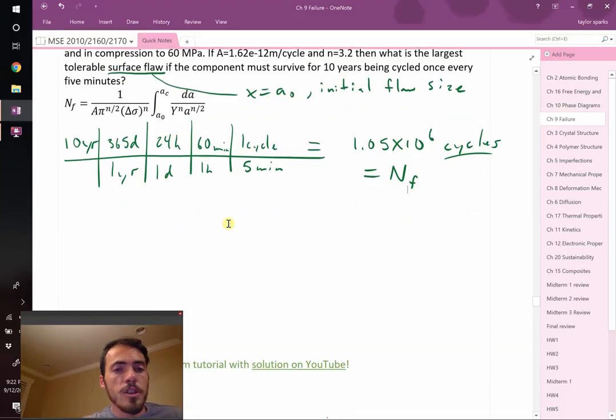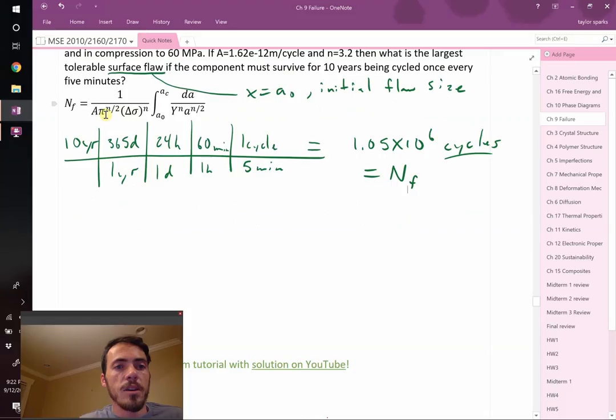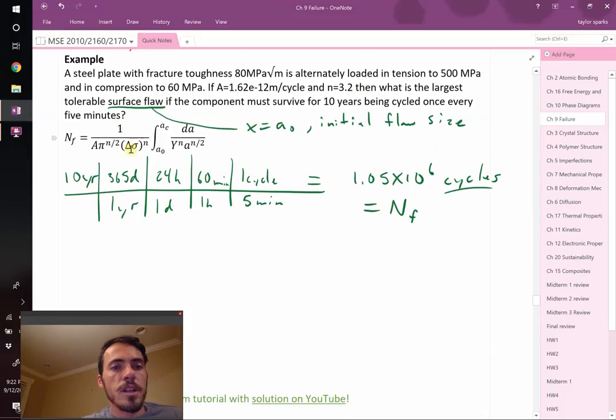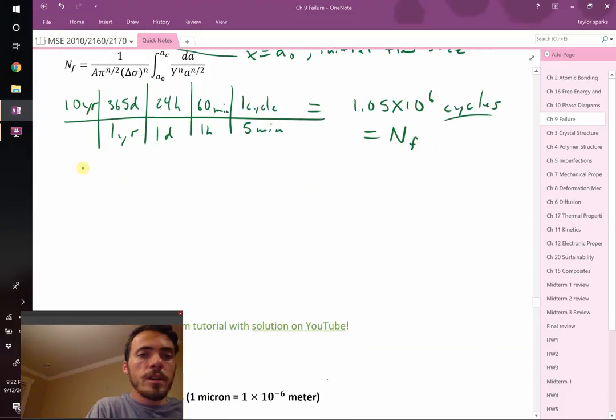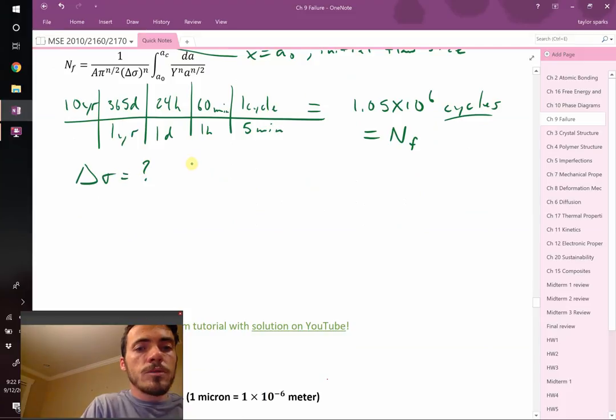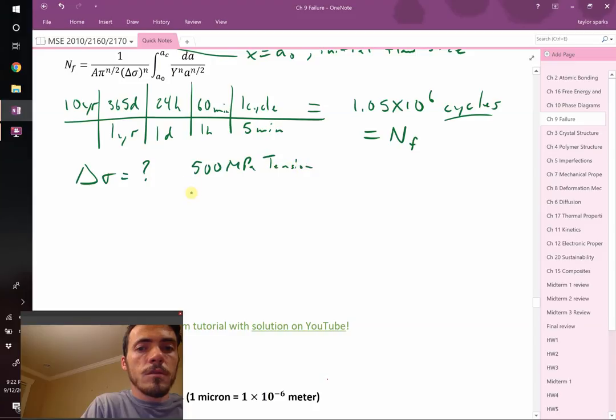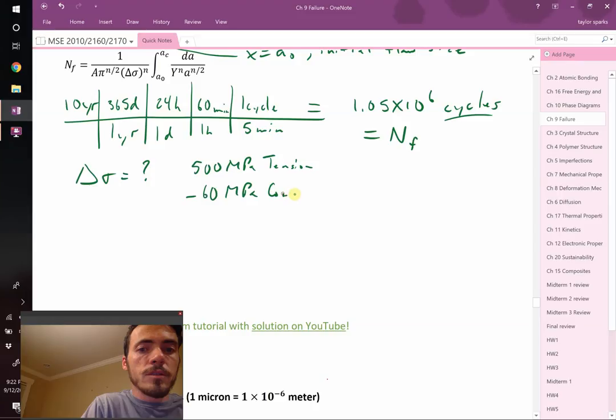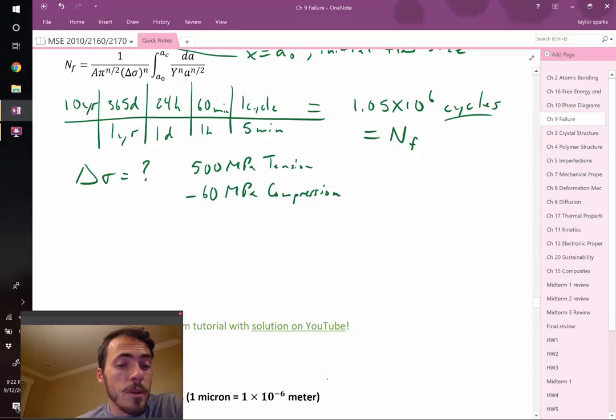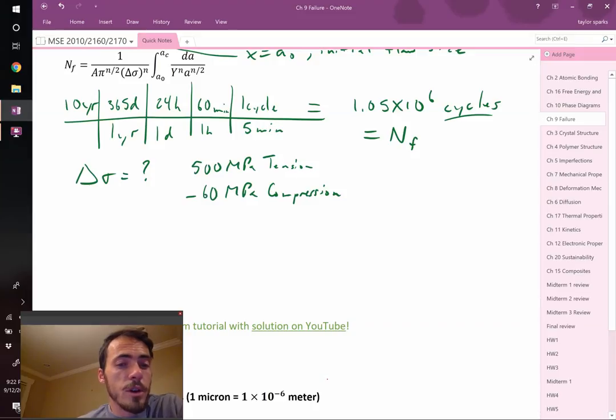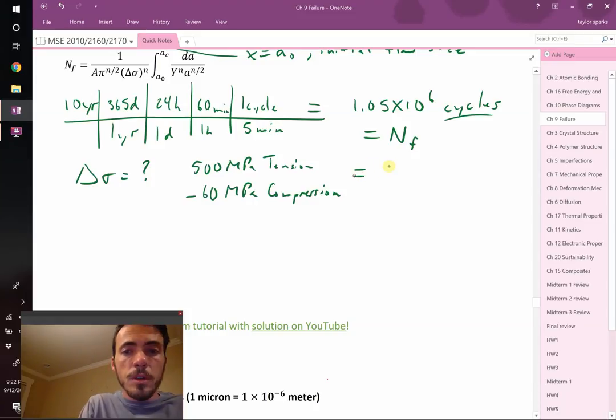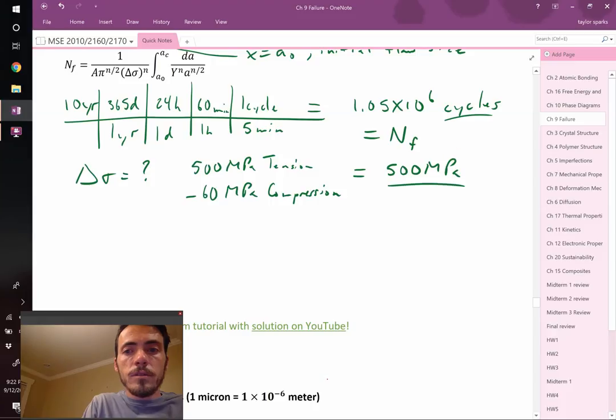We've got nF. In the problem, we're told what A and n are. Pi is a constant. What about delta sigma? It's ranging from 500 megapascals tension all the way down to negative 60 megapascals compression. It might be tempting to say that the range is 560, but remember that's a mistake because in this class we're assuming cracks only grow under tension, not under compression. So delta sigma is just going to be 500 megapascals.